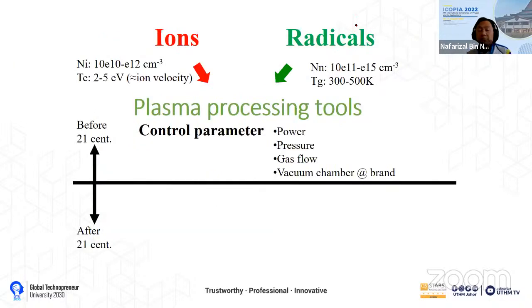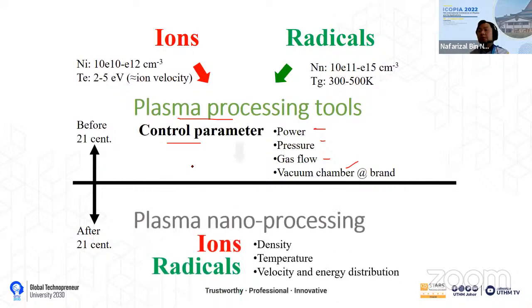So this plasma processing is also very critical. Before this, all the researchers and the industry controlled the plasma process by controlling the parameters. So they control the power, the pressure, the gas flow, also maybe the design of the chamber. So this is before. And nowadays, we would like to propose that instead of controlling these parameters, we should control the fundamentals inside the plasma.